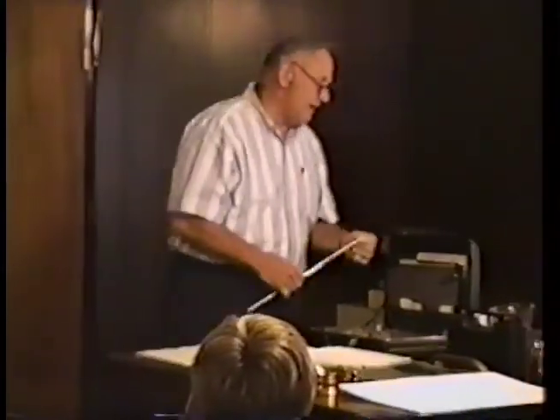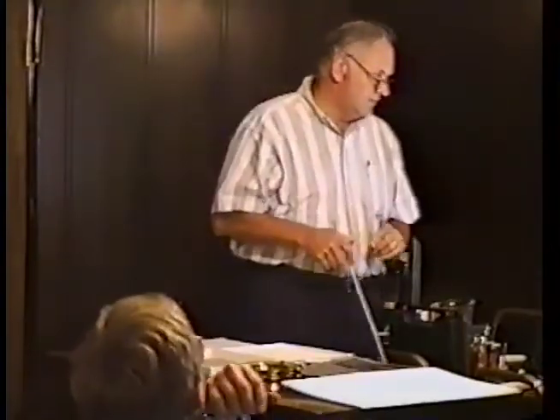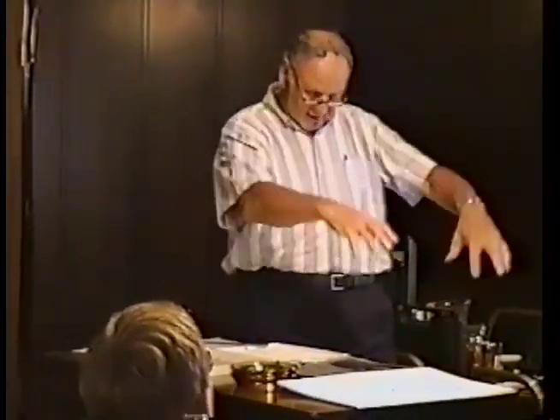We talked about the cleanliness of the surface and things of that sort. Something as little as laying a hand on that board to move the liner can cause enough contamination of that surface to affect adhesion. So care must be taken, and you really mustn't prepare the liner too far in advance of when it's actually going to be wrapped up and plated, because it can affect the bond.